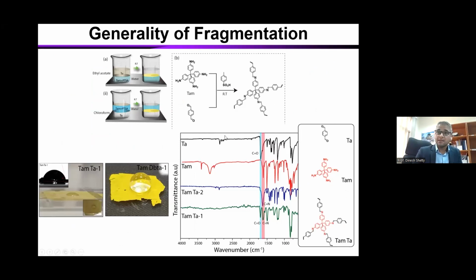So then what we did, is it true? Is bromine really the reason for this? Then what can we do? A simple control experiment. We took the same tetraamine and then we took a linker without bromine. Here also we end up getting a similar tendency. When we observe the FTIR and all other characterization, we observe the defect fragmentation nature is the same. We observe the generality in the fragmentation nature. When we have ethyl acetate, we have more fragments or defects, and when we have chloroform, we have less. But the interesting thing here is that with the linker without bromine, even with the fragment system, the hydrophobicity is not to this extent.